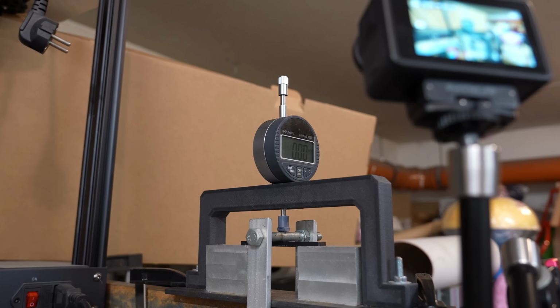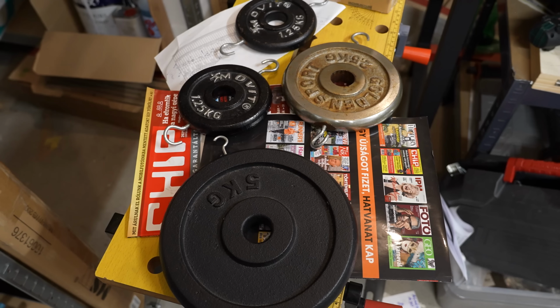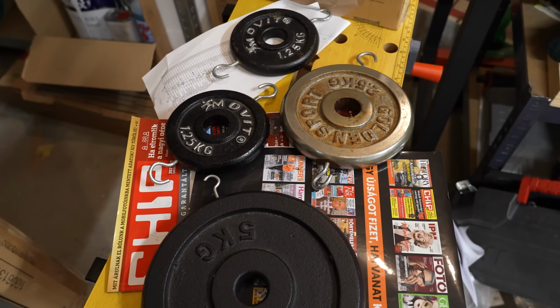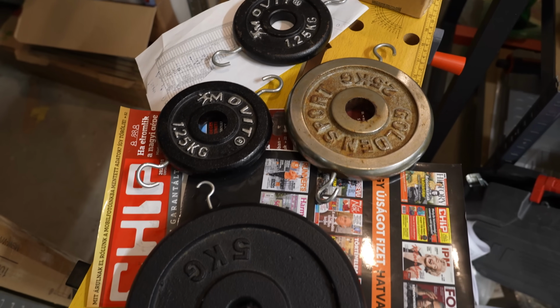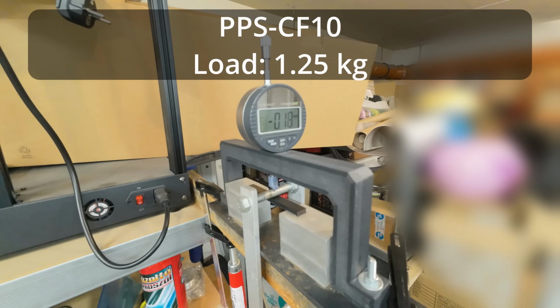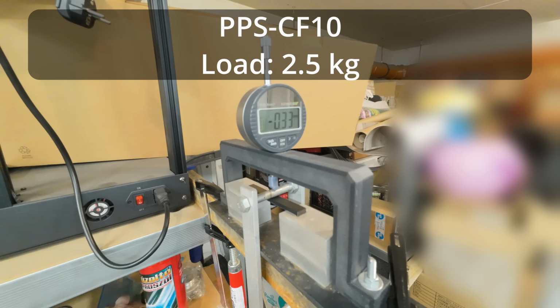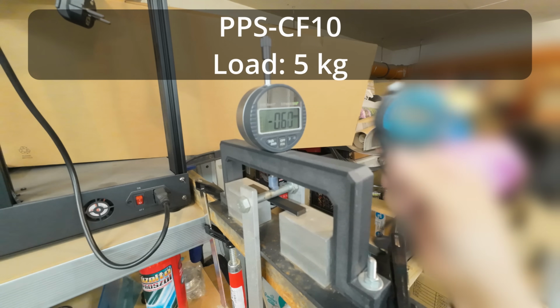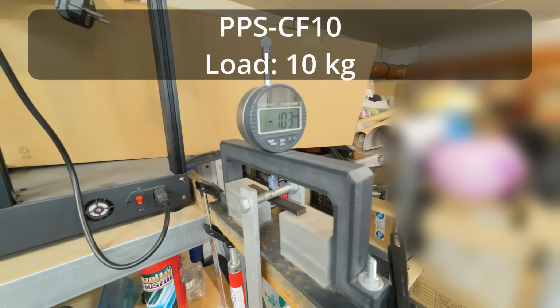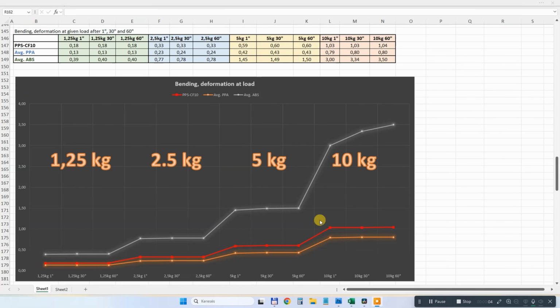3-point bending test, distance between supports is 50 mm, and these loads will be placed one by one, and I'm measuring the deformation after 1, 30 and 60 seconds. This is a deformation under 1.25 kilograms, under 2.5, under 5 kilograms, and pay attention, almost no additional deformation during the time, even under 10 kilograms. Compared to the PPA, it has slightly more initial deformation, but compared to the ABS, look at this, how big deformation is on the ABS, and here we don't have additional deformation even under 10 kilograms.